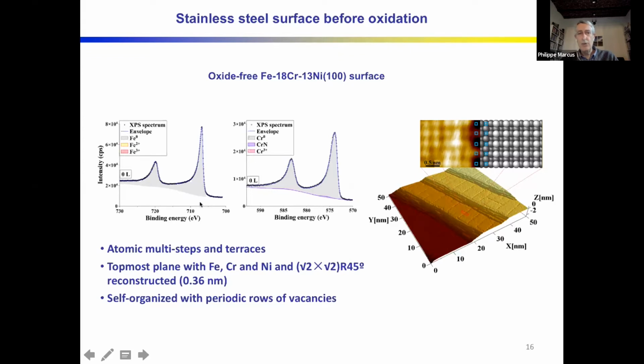And you can see by looking at the XPS that it's extremely clean. There is absolutely no oxide. This is the iron signal here. And this is here the chromium signal. We don't show nickel because nickel is anyway not oxidized. But you see that it's a purely metallic surface.